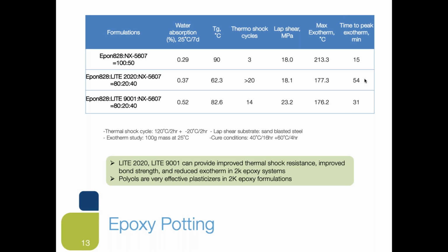gel time. So Light 2020 and Light 9001, and even other polyols, can be used in epoxy systems to improve thermal shock resistance and bond strength and reduce the exotherm. And I highly recommend the polyol as a very effective plasticizer in 2-component epoxy formulations.